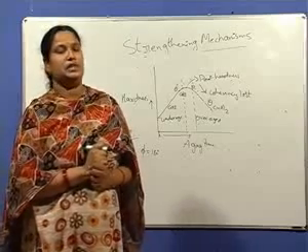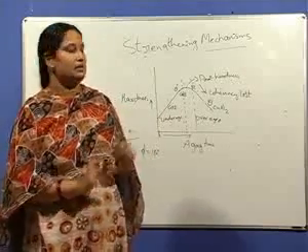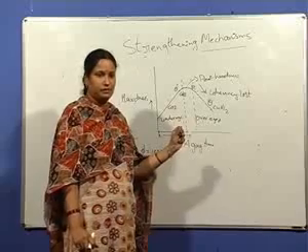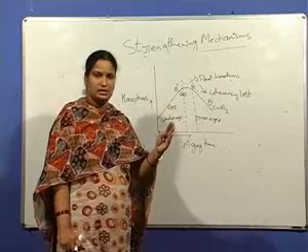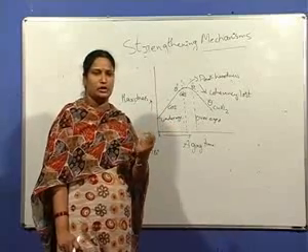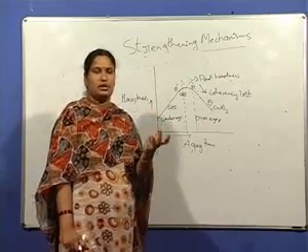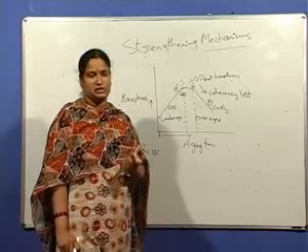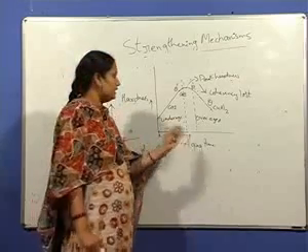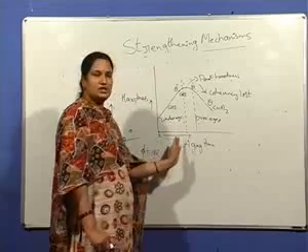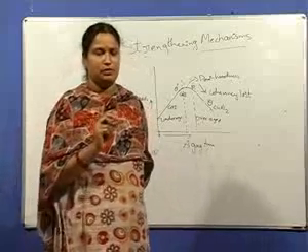And in the case of precipitation hardening alloys, one example is the aluminium copper alloy, which is discussed now. So initially, after solutionizing, to take all the solute into solid solution, and then quenching to retain the supersaturated solution, and then aging at lower temperatures so as to precipitate the excess solute from the matrix. So in the initial stage, with respect to the aging time, small clusters are formed.